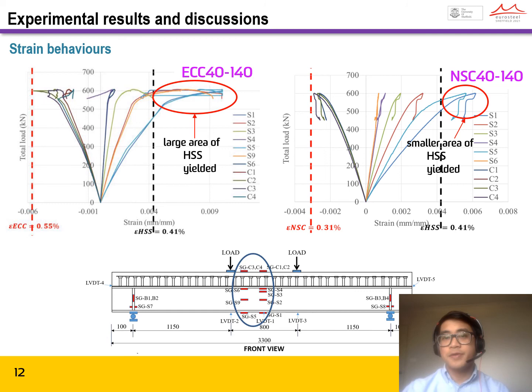It's obvious that a smaller area of high-strength steel yielded compared to the ECC beam. It is also worth noting here that despite this beam failing with a brittle failure mode, NSC almost reached its maximum strain of 0.31%.